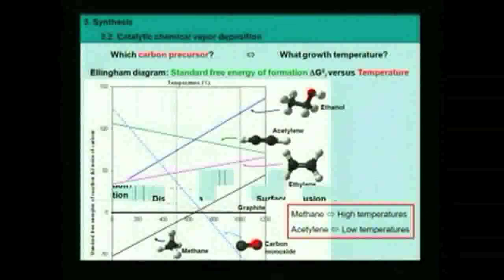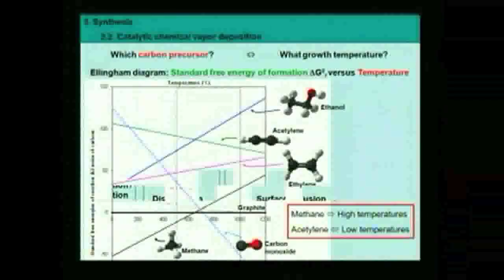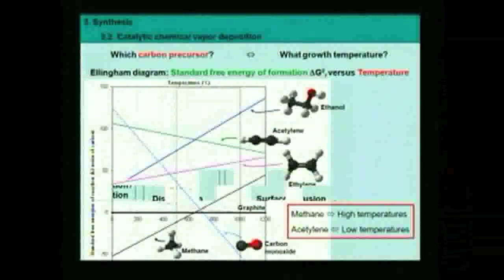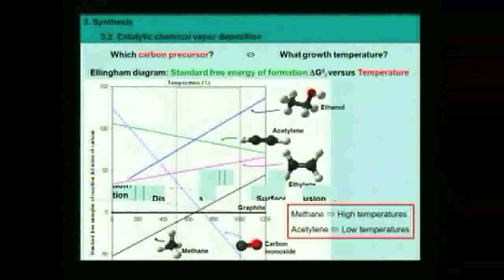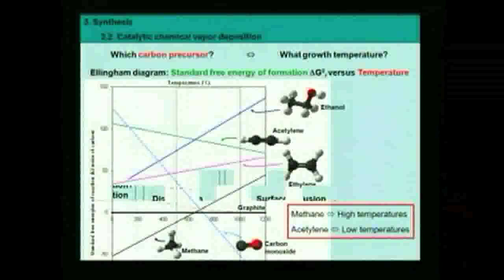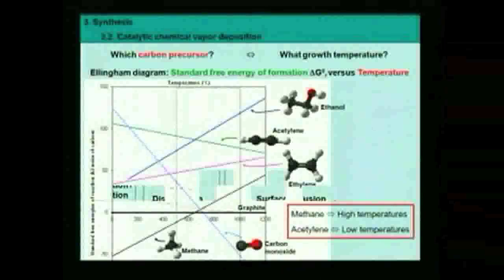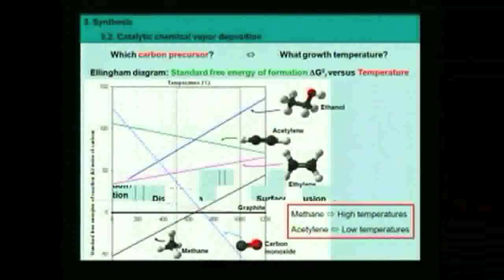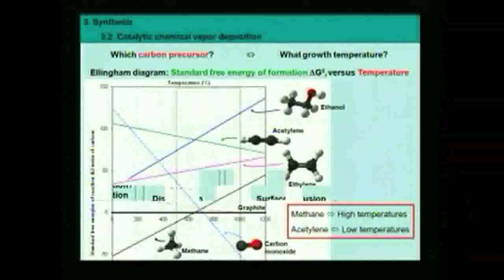Carbon monoxide is a special case because at the beginning of this reaction you have two gaseous molecules, and at the end you have only one. It means that the entropy changes a lot, and this is why you have such a negative slope for carbon monoxide. Also, you see that carbon monoxide, like methane, if you increase the temperature too much, then the dissociation of carbon monoxide into carbon will not be thermodynamically allowed anymore.